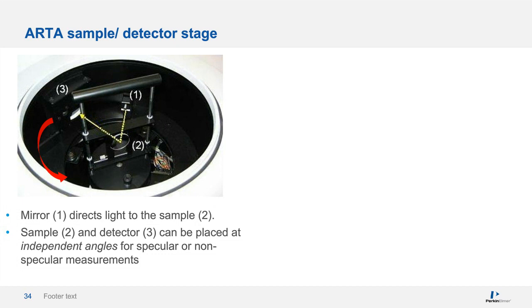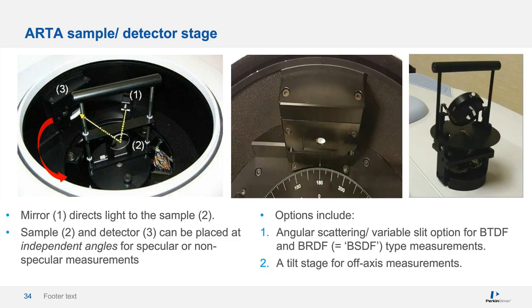And this is seen here where the detector aperture has been modified to reduce the acceptance angle in order to improve the resolution of a scatter type measurement. On the far right, we see a tilt stage, which might be used for scatter measurements in those situations where the sample may not be truly isotropic, and a fuller characterization of the inherent scatter might be deemed necessary.